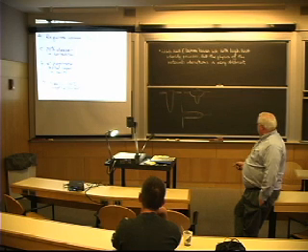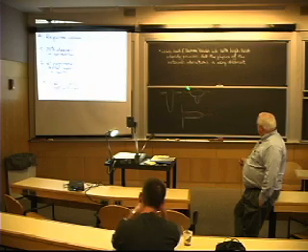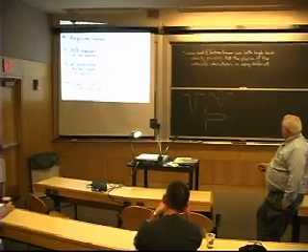And it's hard to read this, but the laser is nearly 100% heat efficient on a ceramic, but on a metal, you have a lot of reflectivity. So you have the free electrons in the metal. The free electrons absorb the laser light and then re-radiate it.